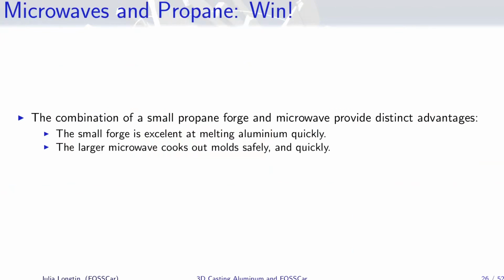As I was saying earlier, the combination of using a small propane-fired forge and using a microwave for your molding techniques means that you get to rapidly do this process. I have, in periods of about 4 to 5 hours, gone from 3D printed thing to waiting for my aluminum to cool, versus the standard process, which sometimes can take days, depending on how thick your mold is.